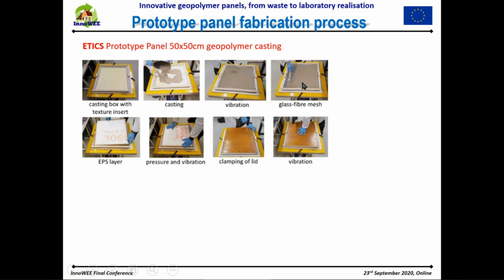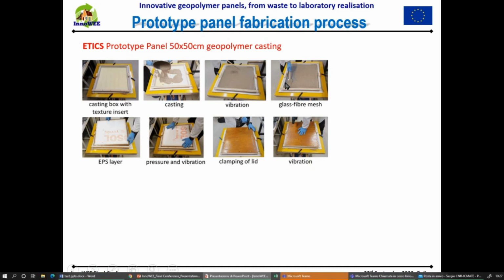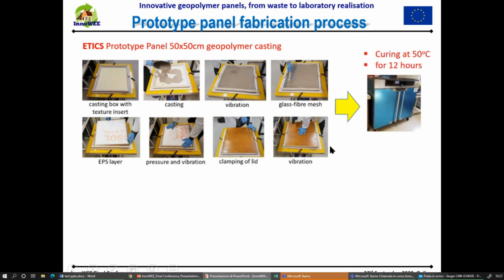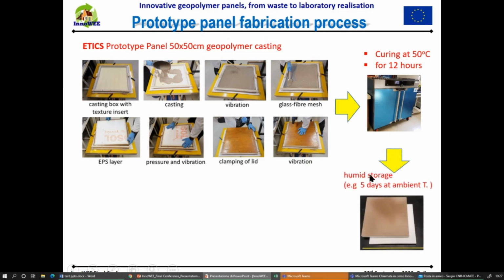Then we put a fiberglass net, then the EPS layer, again pressure and vibration, then everything is closed with the lid, and after vibration the panel is placed in a sealed bag in an oven for curing for 12 hours. Then after 5 days of humid storage, the panel is ready to be worked to finish with painting, for example.